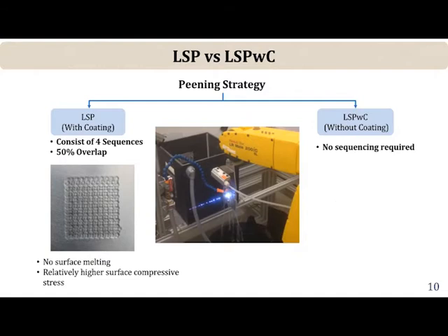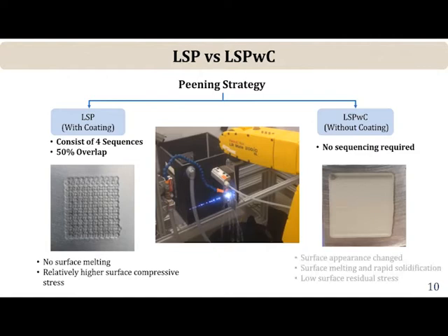But when you do this without a coating, basically no sequencing is required. But in the case of these aluminum alloys, you can see that the surface appearance is completely changed, right? And as I mentioned, you can do this under flowing water or underwater, okay? And when you do this without a tape, you get surface melting and rapid solidification. The surface residual stresses can often be tensile, or slightly compressive, depending on what the pulse density is, how many spots, number of impacts you've put per unit area. But you can see that something has happened, where presumably you've got some kind of an aluminum oxide layer that has formed.